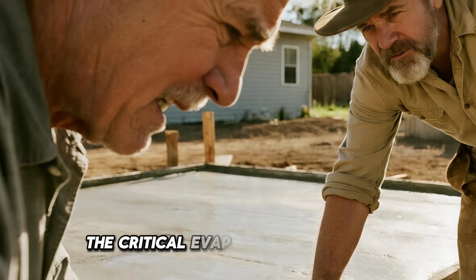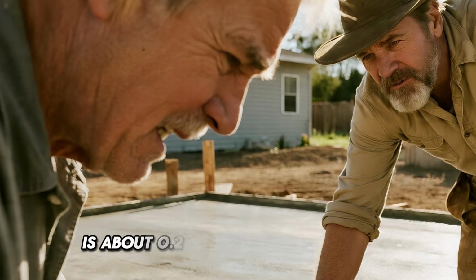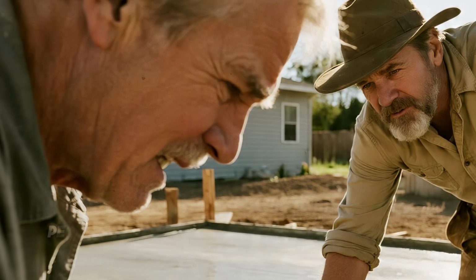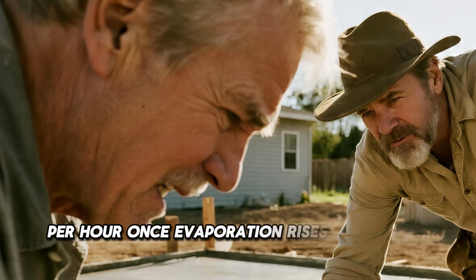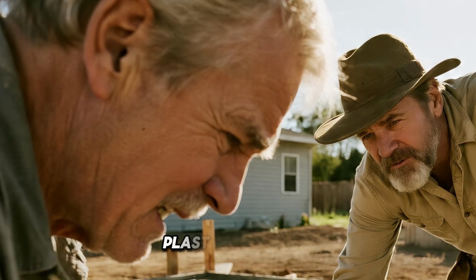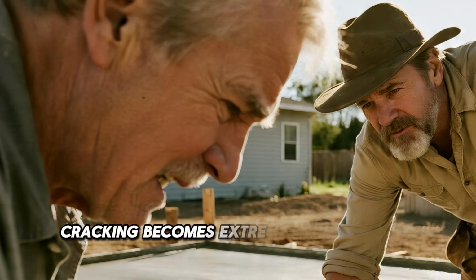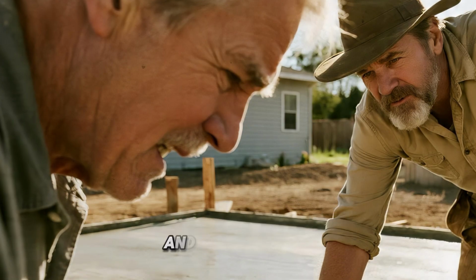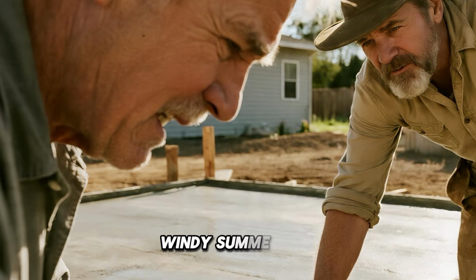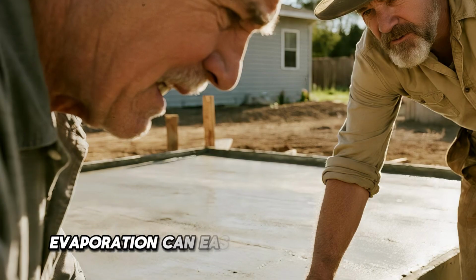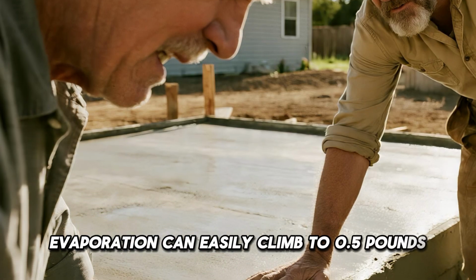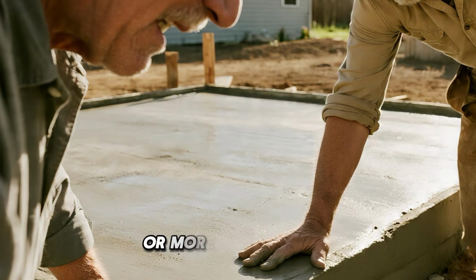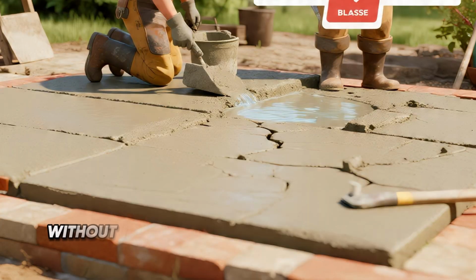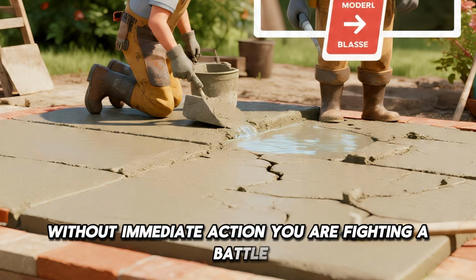The critical evaporation threshold is about 0.2 pounds per square foot per hour. Once evaporation rises above that level, plastic shrinkage cracking becomes extremely difficult to avoid. And on a hot, dry, windy summer day, evaporation can easily climb to 0.5 pounds per square foot per hour or more. At that point, without immediate action, you are fighting a battle that becomes almost impossible to win.